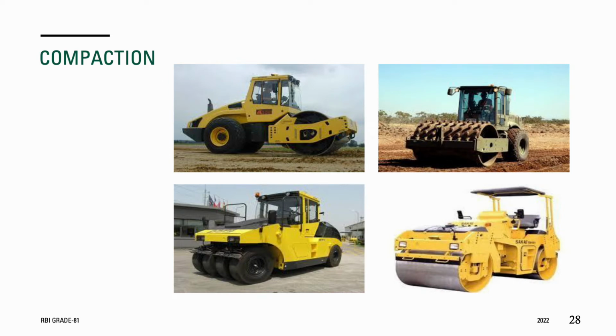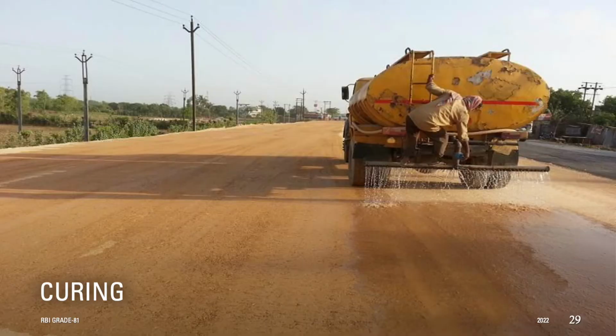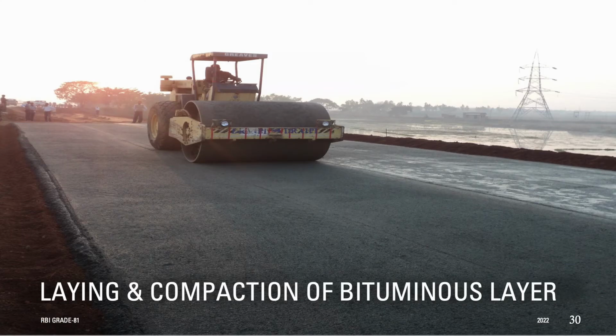Various types of rollers may be utilized for compaction upon completion of mixing. Once the stabilized layer is compacted, it is to be cured to avoid any moisture loss from the mix. The compacted layer should be cured for a minimum of 7 days or until the next layer is laid, whichever is earlier. The surface bituminous course is then laid on top of the prepared base layer.